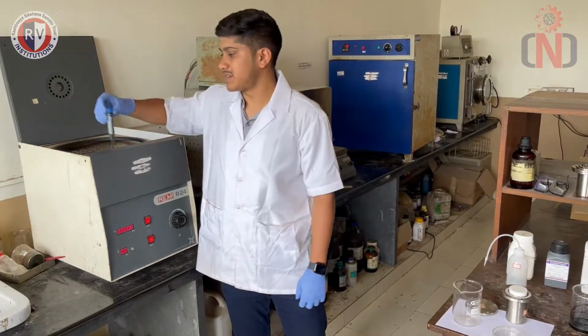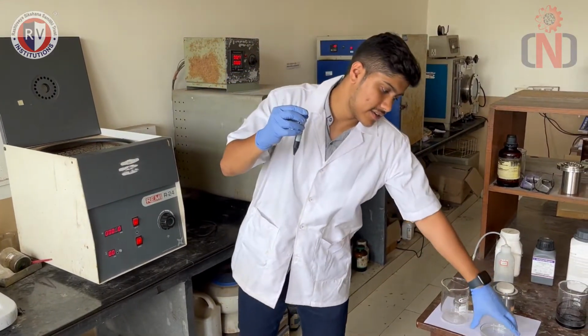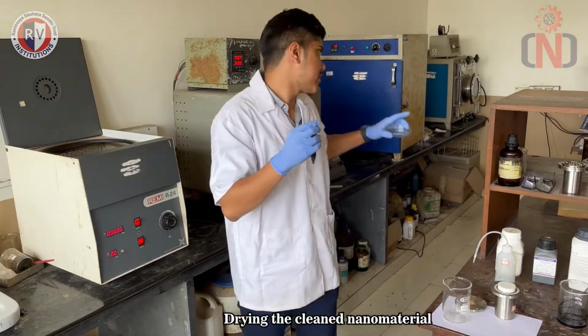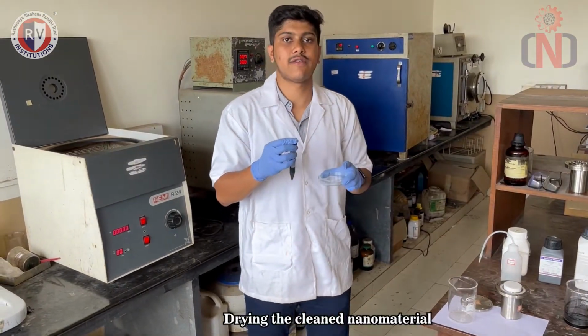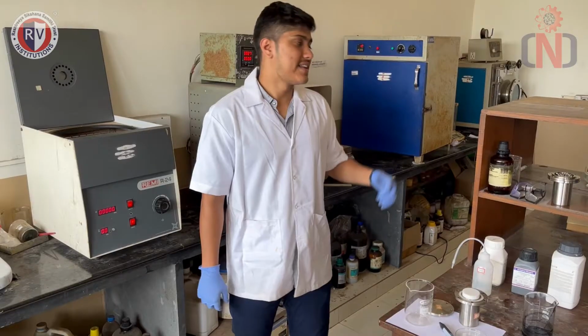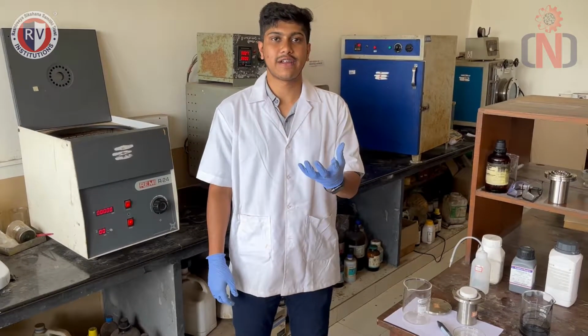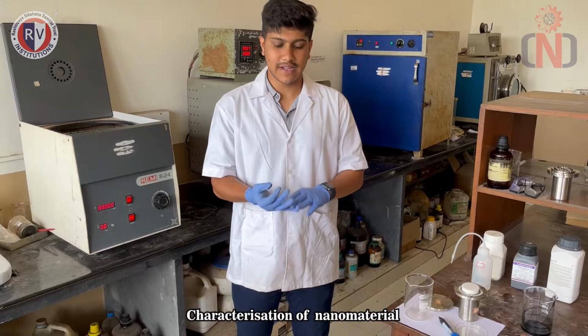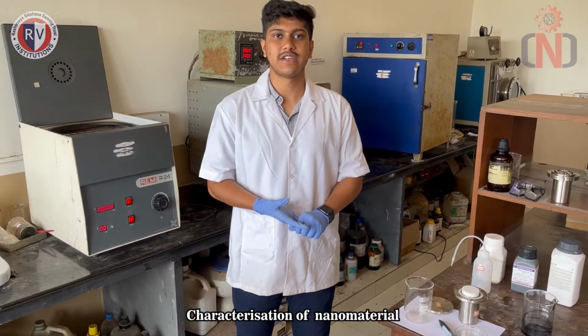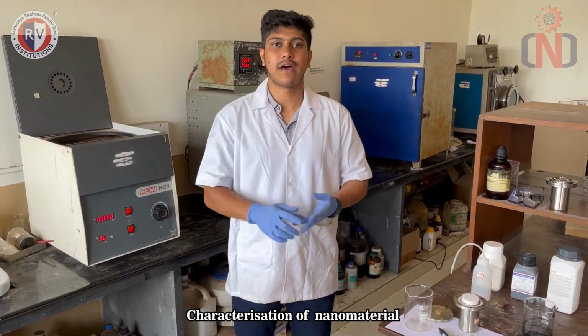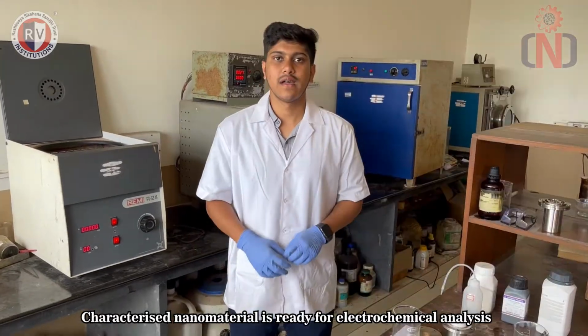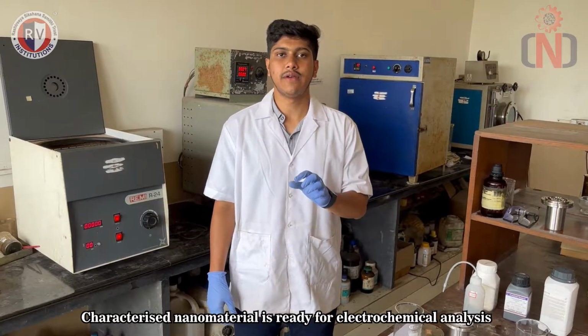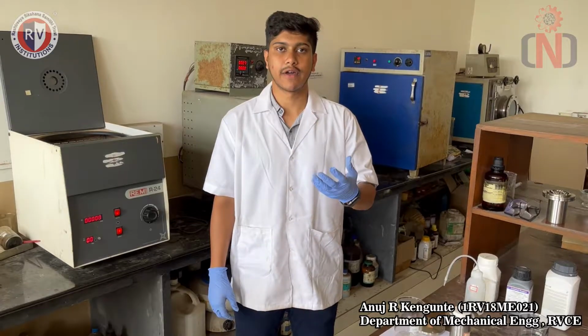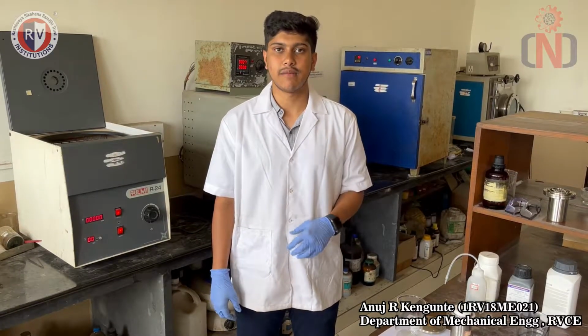After the centrifuging process, the clean product is transferred into this petri dish. This petri dish is kept in the oven at 80 degrees Celsius for 30 minutes for drying. The dried product is taken out and then tested for its crystallinity, purity and morphology using tests like XRD, SEM, Raman and other characterizations. After the characterization, the nanomaterial is used to make a working electrode for testing of supercapacitor applications.